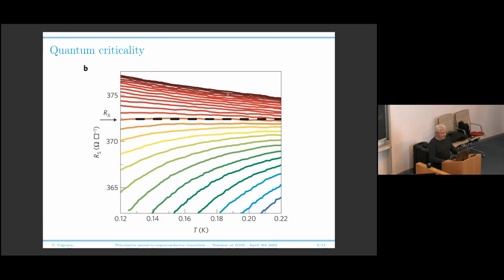This is just an enlarged view of the two. It is much simpler now to plot your isotherms as a function of the magnetic field. So, the point where all the curves as a function of the magnetic field cross is the point where your resistance is independent of the temperature, because all the isotherms cross at that point. So this is a very nice way to detect the crossing point, the point where your resistance is almost independent of the temperature, because all the various isotherms cross there at this magnetic field here.